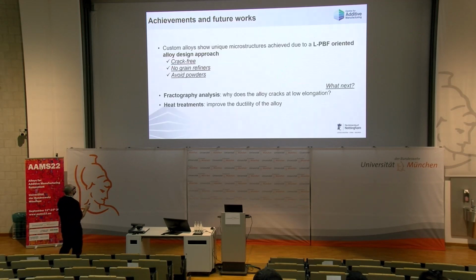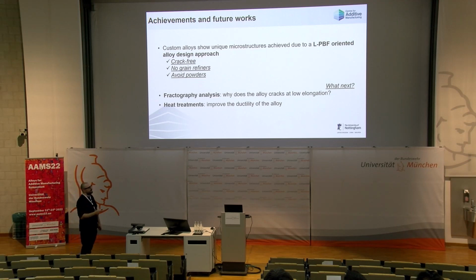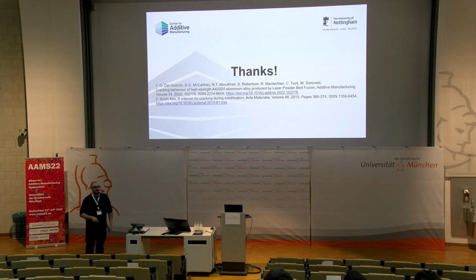So to conclude this presentation, our custom alloy shows a unique microstructure achieved due to an L-PBF oriented alloy design approach, which of course is crack-free, has no grain refiners, and we avoided the use of any additives in the alloy design approach. Next, of course, we want to know why this alloy cracks at fairly low values of ductility, performing treatments to improve this. Thanks, and I'm here for your questions.